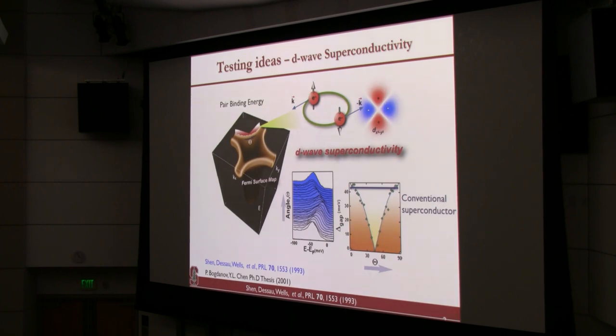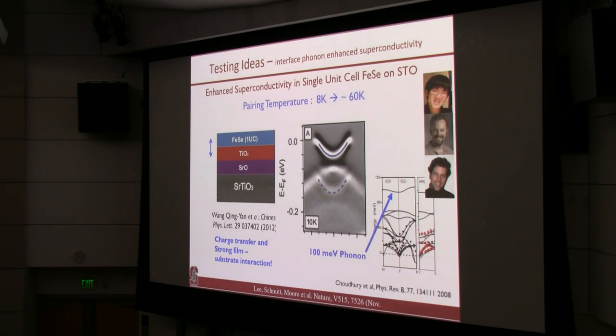Another idea you can test in a superconductor was discovered by a group at Tsinghua: if you grow one unit cell of this superconductor, a monolayer, on a substrate of strontium titanate, you find that the superconducting transition goes from 8 Kelvin to 60 Kelvin. So it's a dramatic difference. The question was, they suspected that the interface did something. Okay, so that's the idea they tried to test.